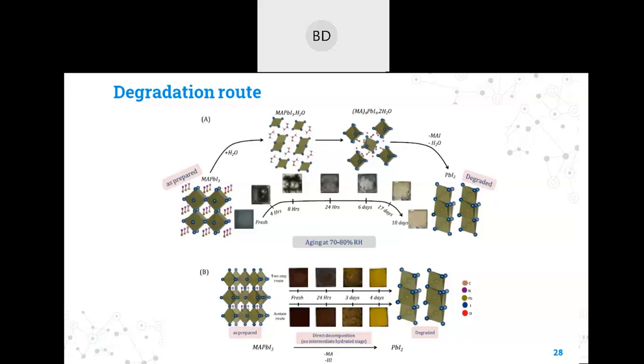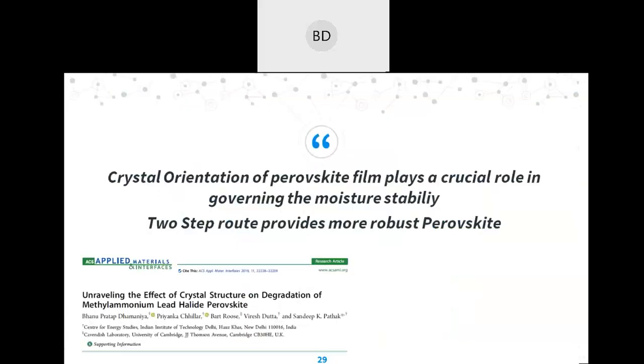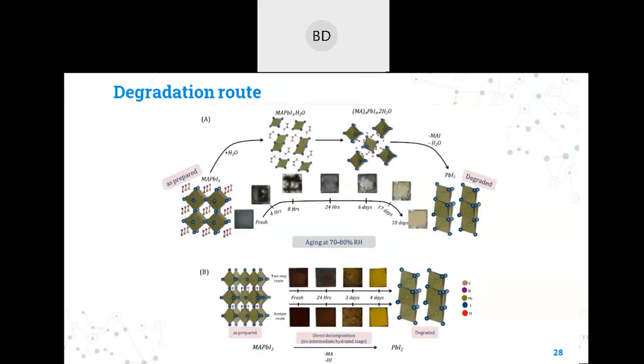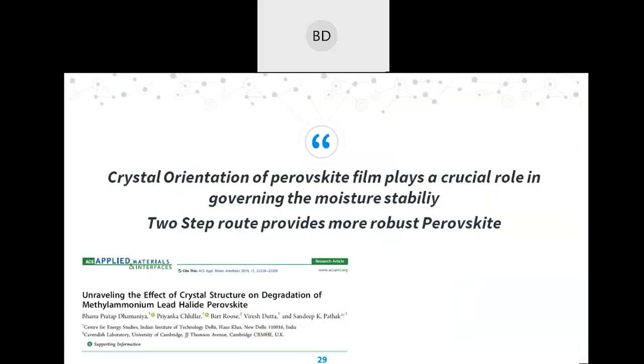So this is how the degradation is happening. The degradation rate and the degradation mechanism differ between all these three routes. From these observations, we came to know that the crystal orientation of the perovskite films plays a very crucial role in governing the moisture stability of the perovskite. And we identified that the two-step route has some kind of resistivity to the degradation. It degrades a little bit slower due to its inherent nature of the perovskite and PbI2 on the top surface, which acts as a protecting element for some time.